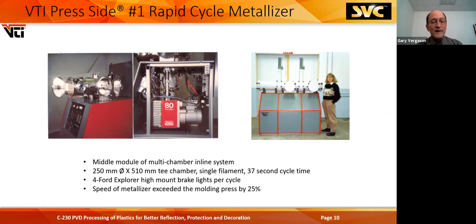It had a single filament in the door, right over here. And one thing we learned very early on was when you put a little boron nitride shield behind that filament, that caught about 90% of the evaporant that went backwards. At the end of the shift, you could put your fingernail on the edge of the boron nitride plate and pull that sheet of aluminum off, and it helped to keep the back door very clean.